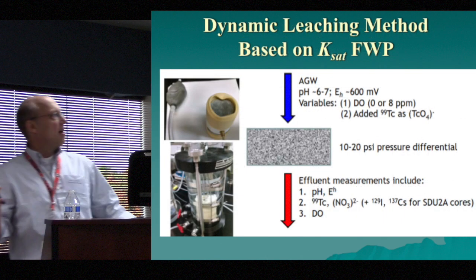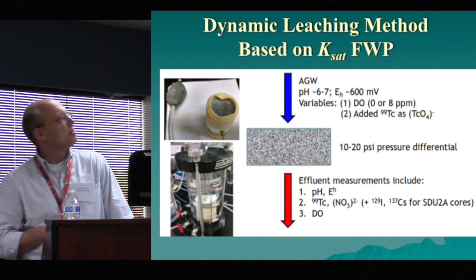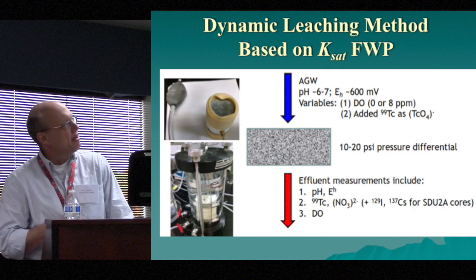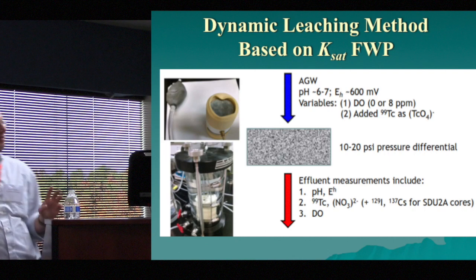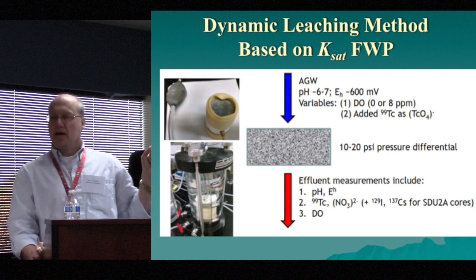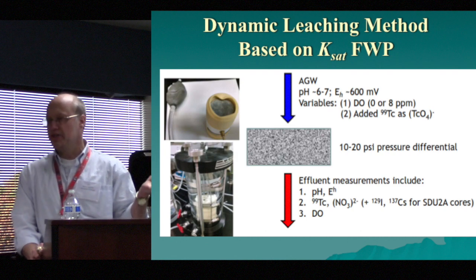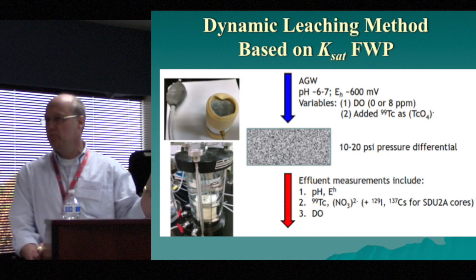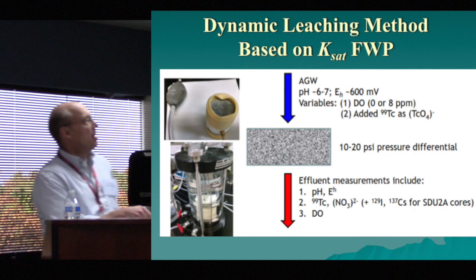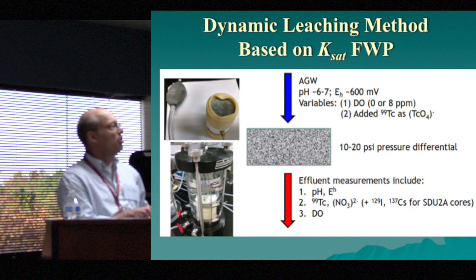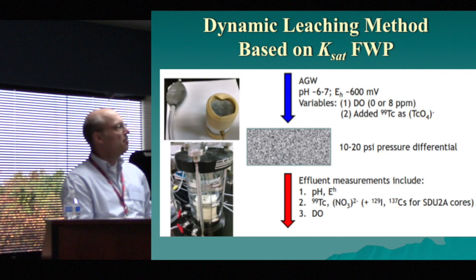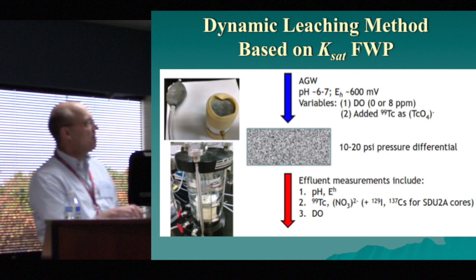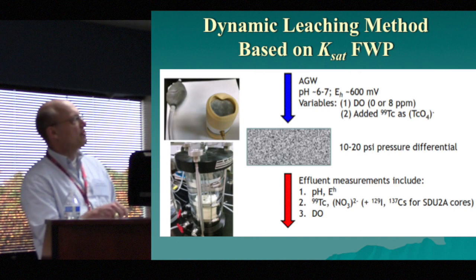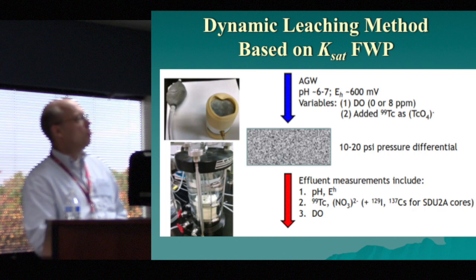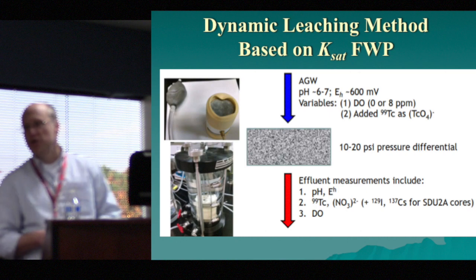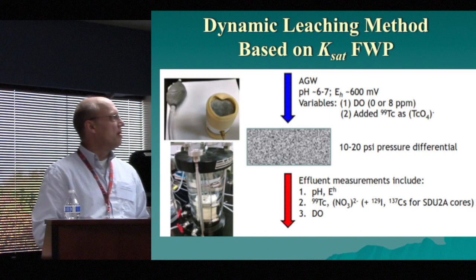So we were talking about measuring saturated conductivity, and we did a lot of these measurements on some simulated materials. And what we found is that even if it was around 1 times 10 to the negative 9, we could get continuous leaching through the material at relatively low pressures just by keeping the material in a flex wall permeameter. And right in there is a piece of core that we're putting the flexible membrane on, and then it gets put into the chamber for measurement. What we're doing is forcing artificial groundwater through under pressure, and then we're collecting that at the effluent and measuring how that effluent changes over time.